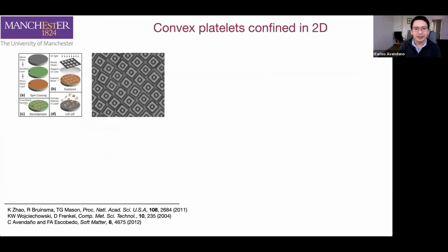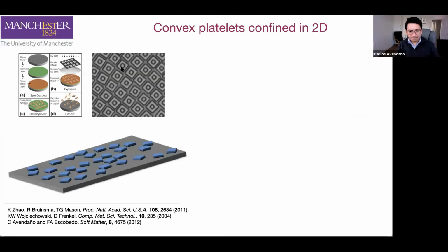Okay, a second example is the confinement of platelets in 2 dimensions. These platelets that I'm going to show you were synthesized using the lithography technique of Thomas Mason that I mentioned to you before. And essentially what Thomas Mason did is to create these particles. He suspended the particles in solution, and by adding a certain amount of polymer in the solution, that will push the particles towards the bottom. So they are not going to have any possibility to rotate. They will be completely absorbed on the substrate. Therefore, they can only move in 2 dimensions.